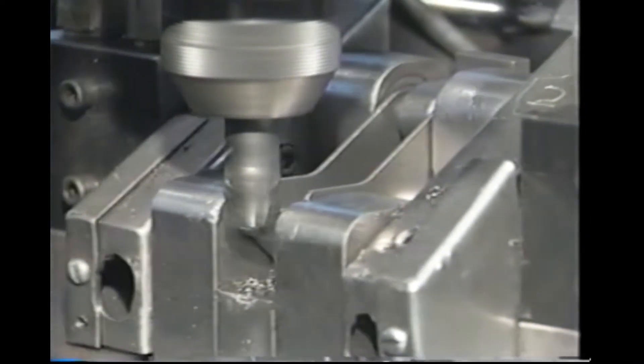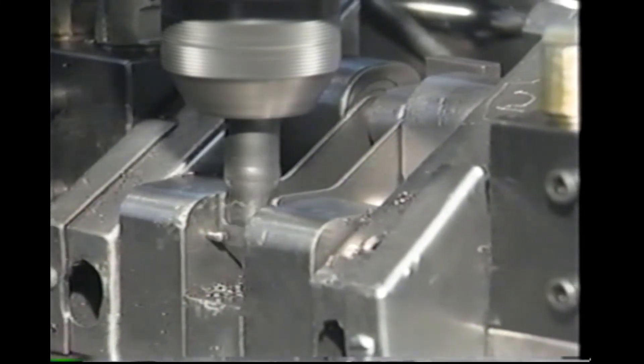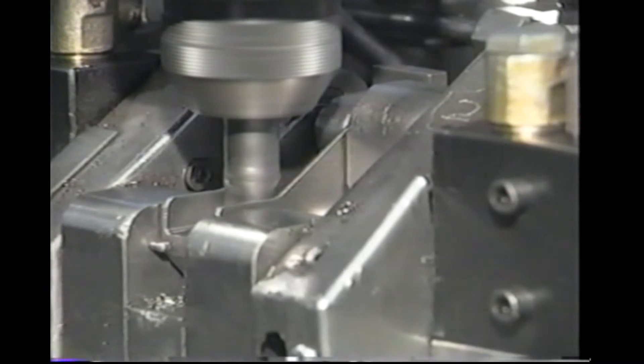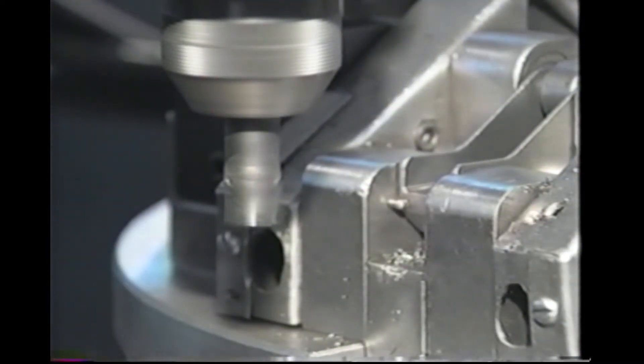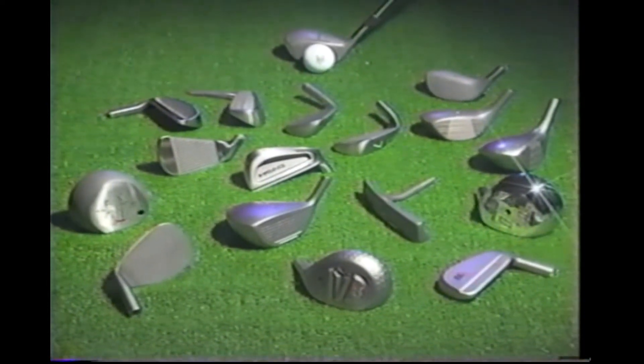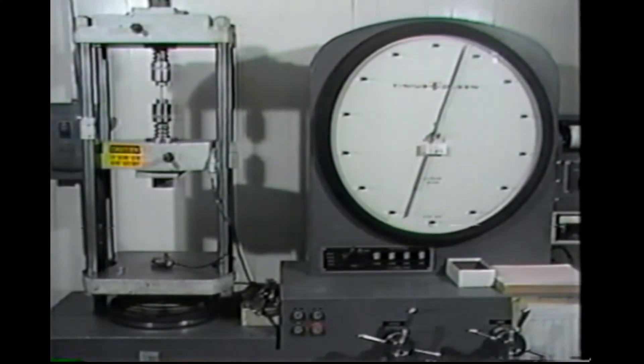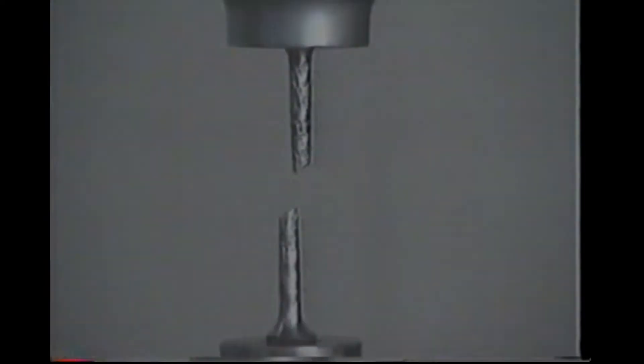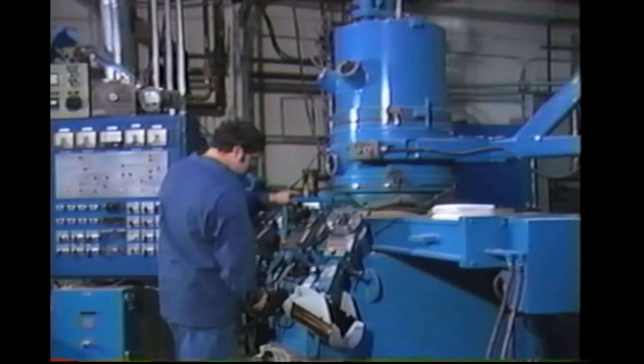This cleaner metal has been shown to reduce tool wear in comparative machining tests done under controlled conditions, giving increases in the life of cutting tools from 100% to 500% depending on the alloy. Very few after-polish defects are found in highly polished CLA cast parts, such as golf clubs. Inclusions are not merely nuisances for production to battle — they can cause premature part failure by serving as sites for initiation of fatigue cracks in highly stressed parts, even though they may not be detected visually after processing.